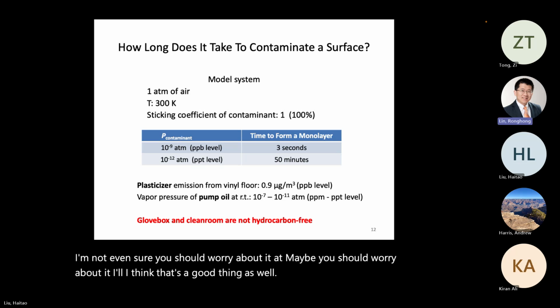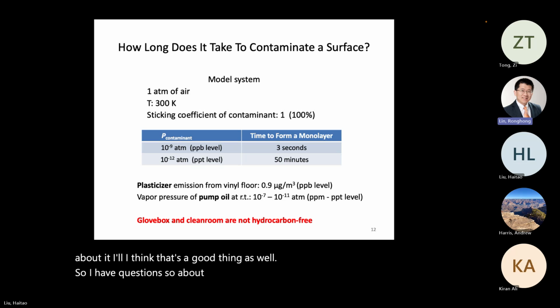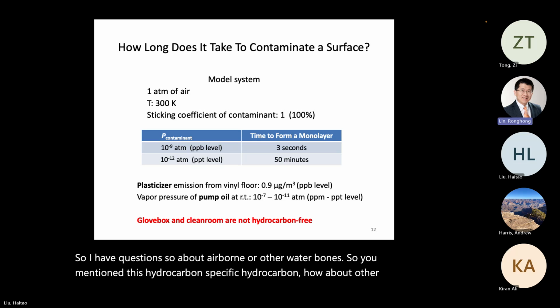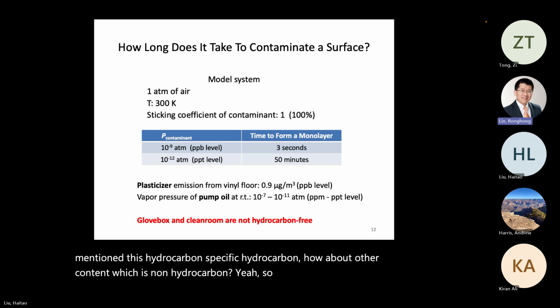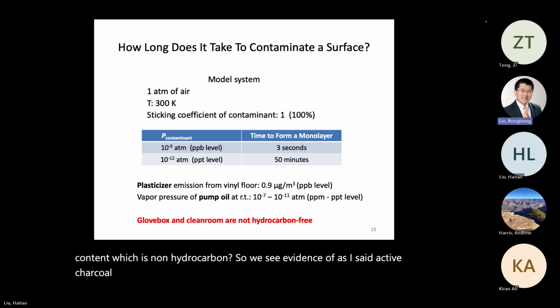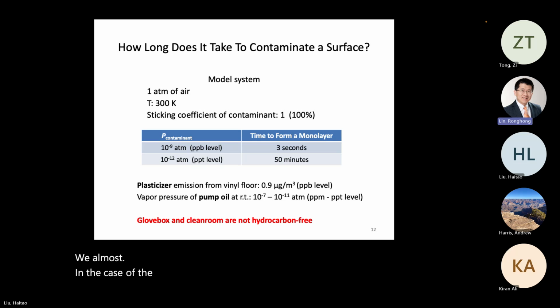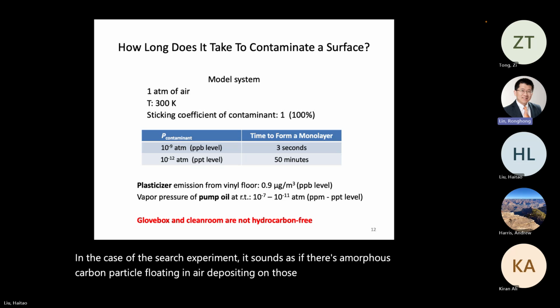So I have a question about airborne or waterborne contaminants. You mentioned this specific hydrocarbon. How about other contaminants which are non-hydrocarbon? Yeah, so we see evidence of, as I said, activated charcoal, amorphous carbon material depositing. So in the case of the experiment, it sounds as if there are amorphous carbon particles floating in air depositing on those surfaces.